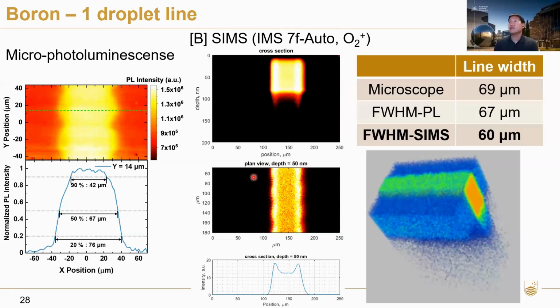And if we put all this together and compare the line width, in this case we measure it using full width half maximum for both the PL and SIMS. We see that there's good agreement. The SIMS reveals a much tighter distribution of about 60 microns, but they're all in agreement, roughly between 60 to 70 microns, which is low enough for an IBC solar cell, where each of the fingers will typically be in the range of around 200 to 600 microns.